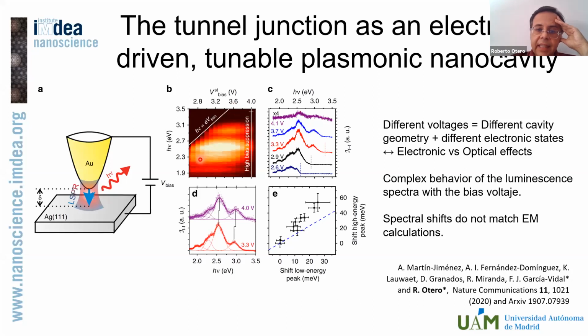But other than that, you can see that the height of the peaks, the peak ratios, actually change. The overall intensity changes so that it starts growing and then it decreases at relatively high voltages. You can observe some shifts in the peaks, shifts of the order of, let's say, 10 to 25 or even 50 milli-electron volts. And then the question is, how many of these changes actually arise because I'm changing the cavity every time that I change the voltage, or how many of these changes are related to the different accessibility of initial and final states when I change the voltage? That's actually the question that we would like to answer.